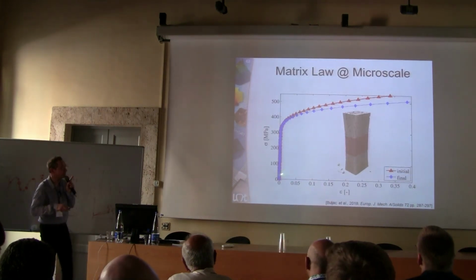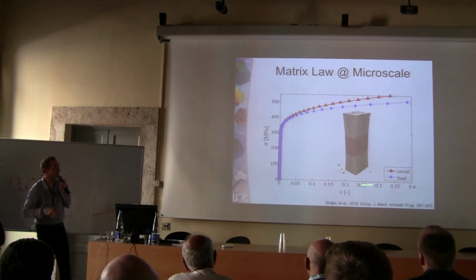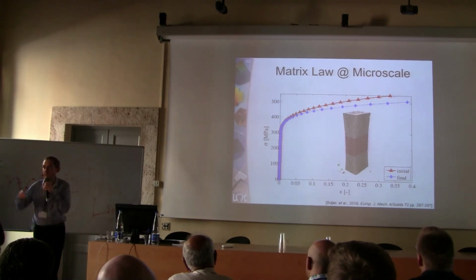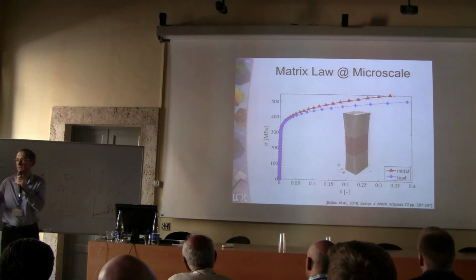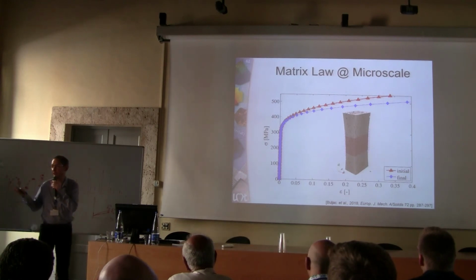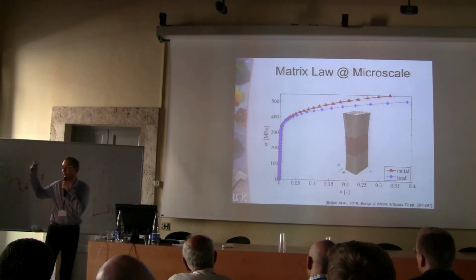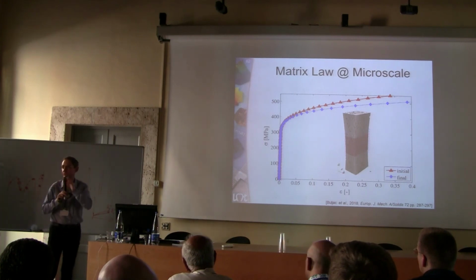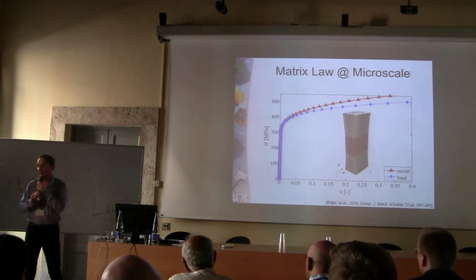The interesting thing is that thanks to tomography you can basically reach strain levels that are very high and that you wouldn't be able to measure from a more macroscopic point of view. So yes, this is indeed possible, but that's the very beginning in DVC to account for nonlinear models.